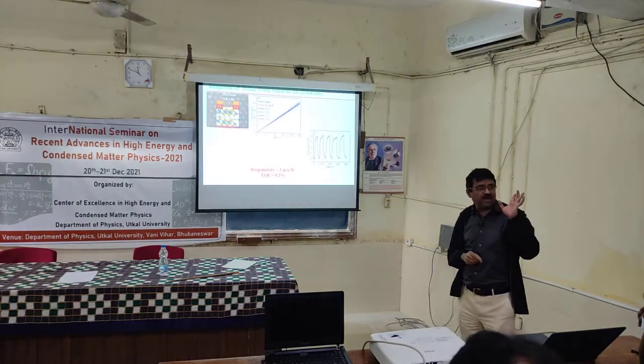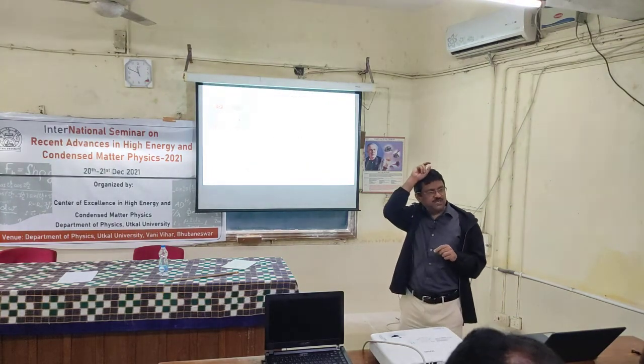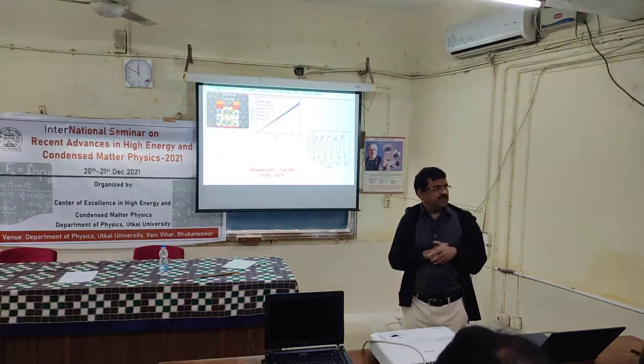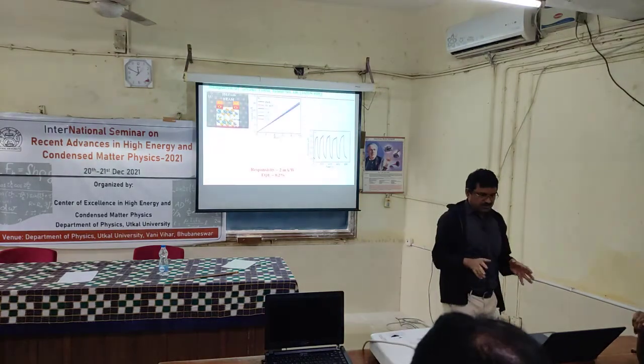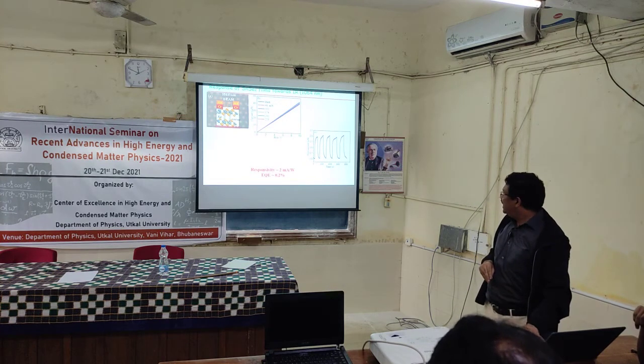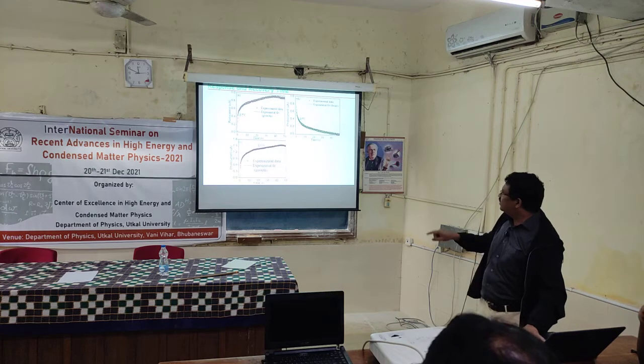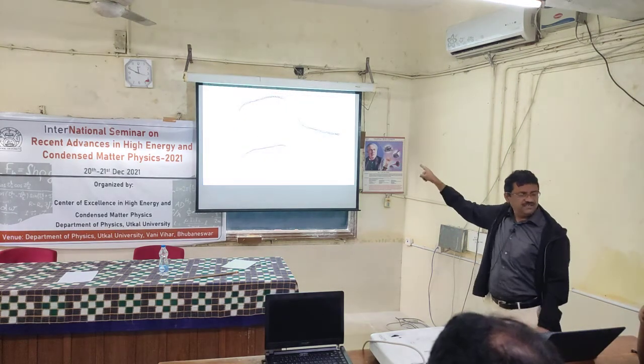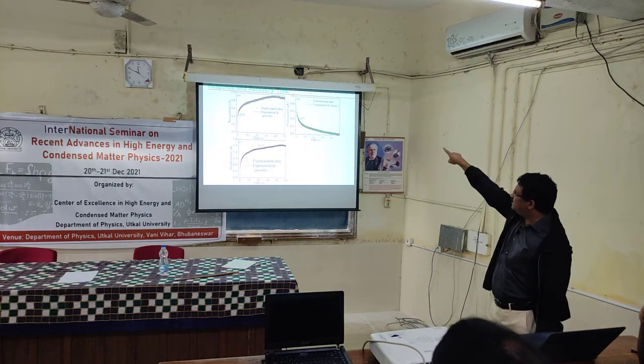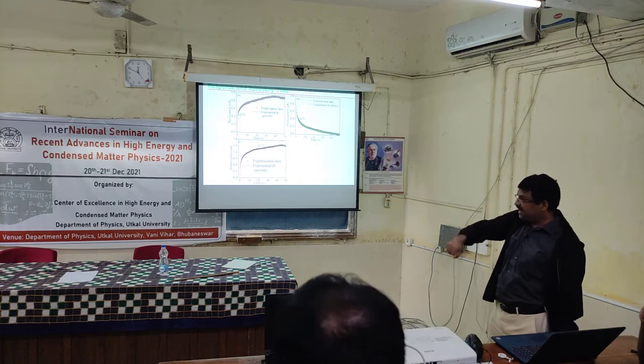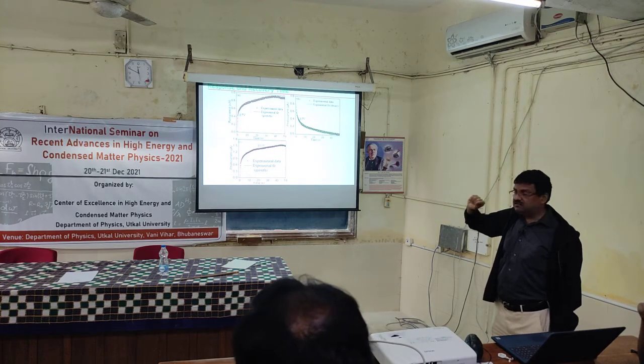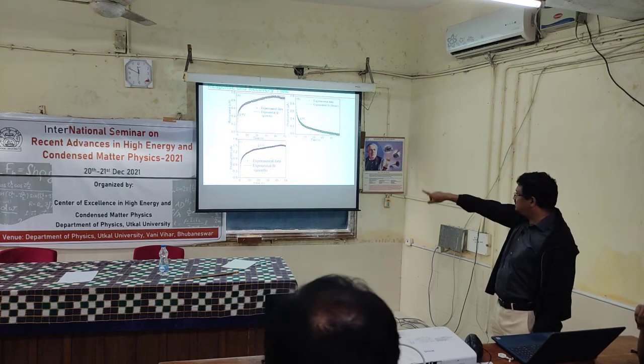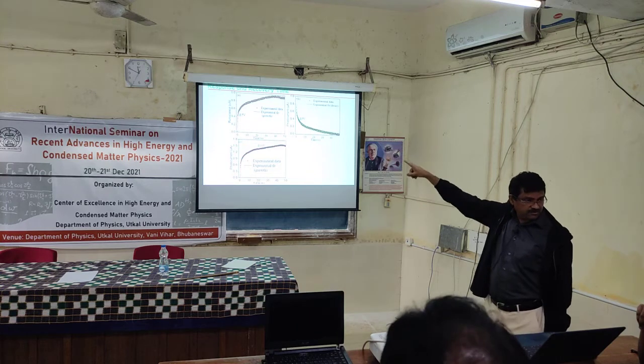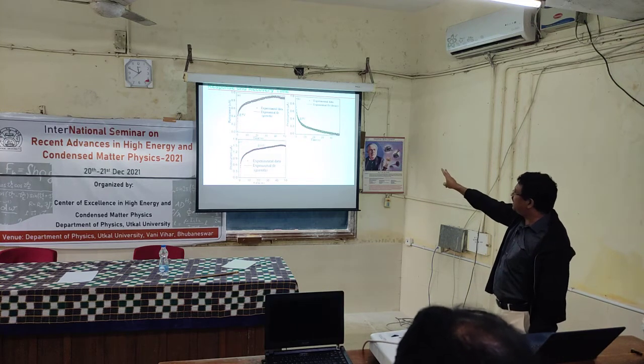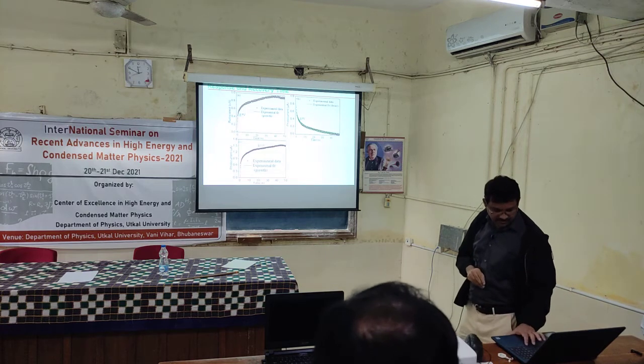So the response time is quite important. You don't have the patience to wait. Suppose the photocurrent is very huge, but it takes 1 hour to come down. Then also it is of no use. You can't wait 1 hour to make another measurement. So the response time should be very fast. You can fit this exponentially. The response time or recovery time follows an exponential decay, and there is an exponential rise. When you shine light, there is an exponential increase in the photocurrent before it saturates. Similarly, when you take it out, there is a decrease in the photocurrent, and that also decreases exponentially. So you can use exponential fitting and find out the response and recovery time.